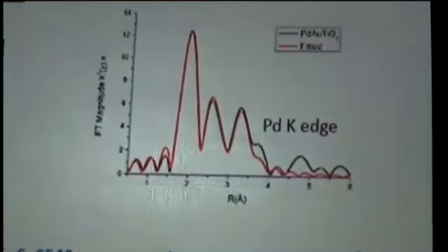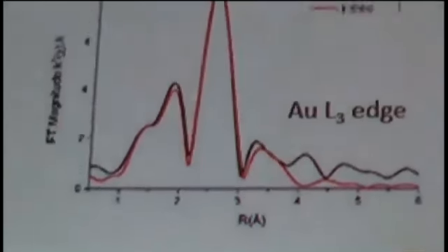So before I go to the catalytic results, first a bit of structure. We quite extensively characterized these catalysts by using STEM-EDX, by using EXAFS, by using XPS, and by using IR spectroscopy after CO adsorption. And these nice STEM pictures were obtained by our collaborators at Lehigh University, Chris Kiely, and they really nicely show that we indeed have control over the size of the nanoparticles. We have quite a uniform distribution with an average particle size of 1.5 nanometers.